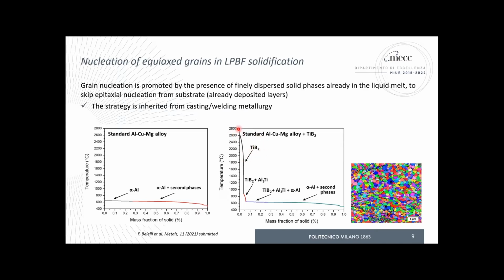Okay, so there will be some solid particles available in the liquid melt already from very high temperature. The solidification sequence in the matrix doesn't change, but we can create some nuclei, some substrate on which the aluminum grain can grow. So first we have TiB2, and then a layer of Al3Ti can form on the former particles, and then we can induce the growth of the aluminum matrix.